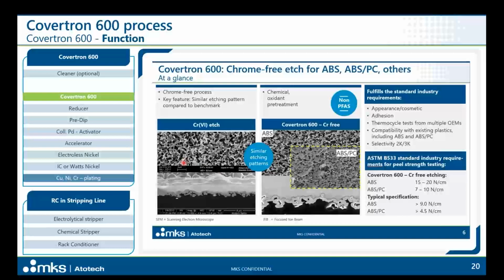And with the Covertron 600, we can use the same sequence, but at the same time giving us good adhesion of the subsequent metallic layers, which will give the plastic part the right decorative finish, and also the right performance in terms of adhesion and thermocycling tests, and the possibility to work with all the different materials, in this case talking also about selective plating. From this point of view, Covertron 600 fulfills all these functions, allowing us to achieve the industry standards.